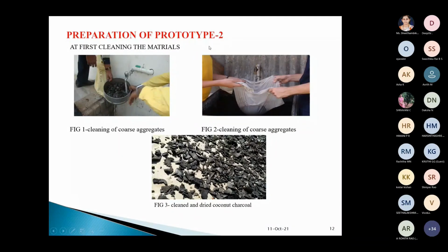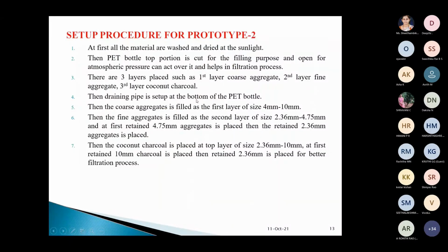And for prototype 2, they have cleaned the coarse aggregate, then cleaned it. Then they have used coconut charcoal, right? Yeah, cleaned and dried it. Setup procedure for prototype 2. It is also almost the same. Three layers are placed: first layer coarse aggregate, second layer fine aggregate, third layer coconut charcoal. Almost the same with the size different.